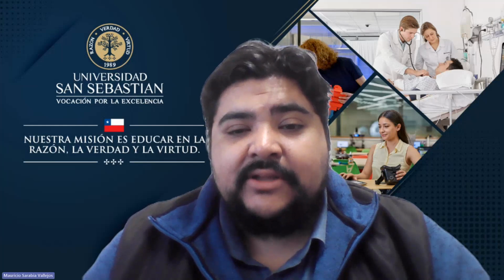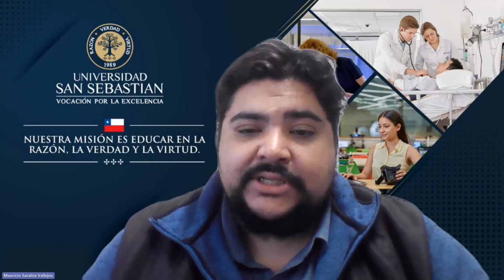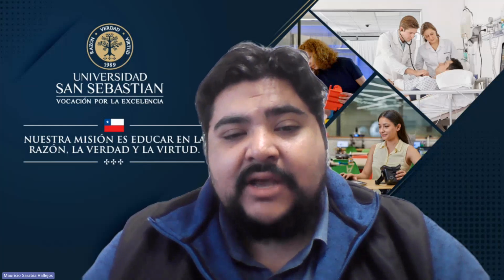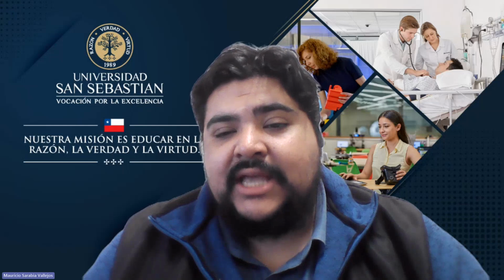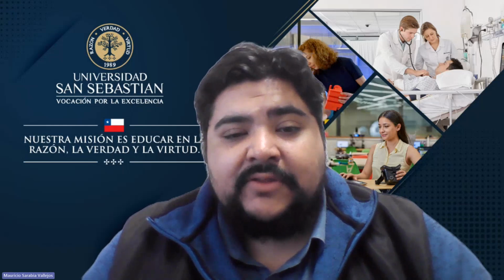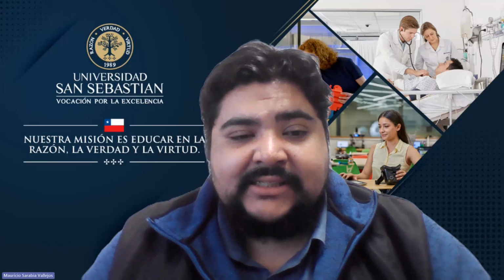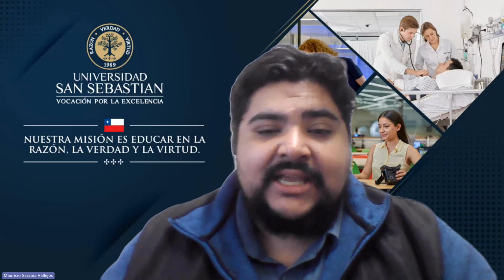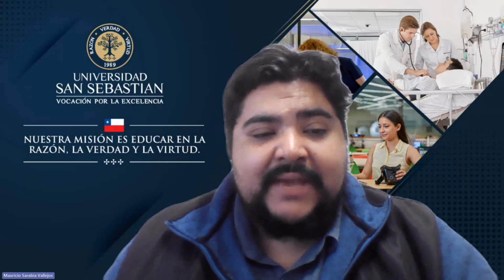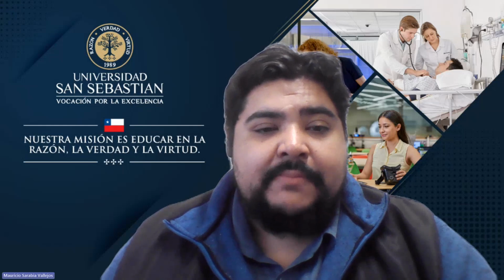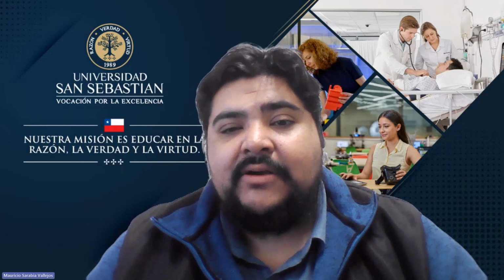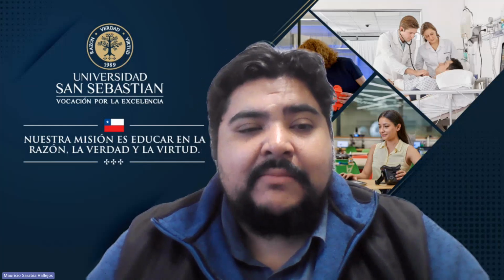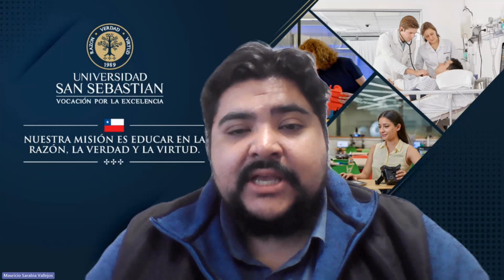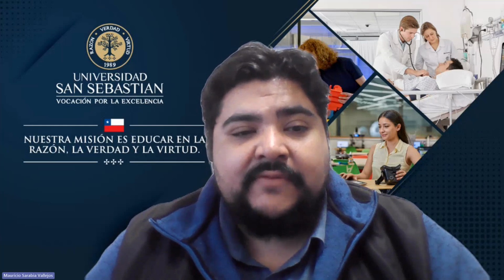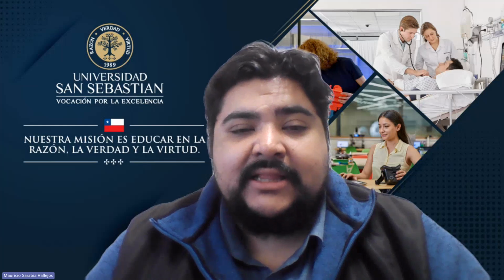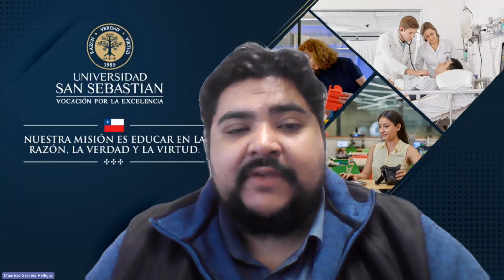One of the biggest problems with this technology, DLP, which means digital light processing, is that there is not a wide variety of materials with which it can be manufactured. From this point of view, our work as material scientists in this field is to develop new materials that meet the necessary characteristics to be used as a base for these biomedical devices. Our work in particular is based on the synthesis of a biocompatible resin based on the PET-RAFT methodology. This type of polymerization route allows the reversible deactivation of the polymer, making it much more versatile from the point of view of the structural modification of the compound.